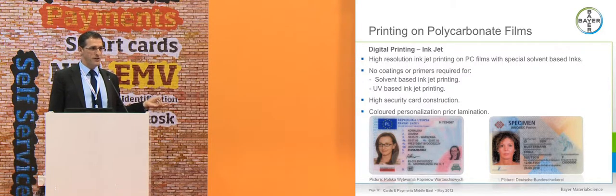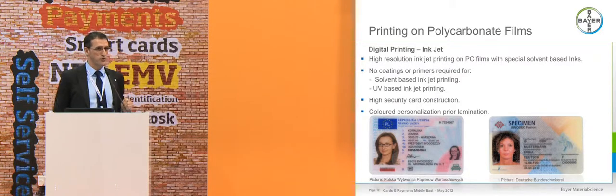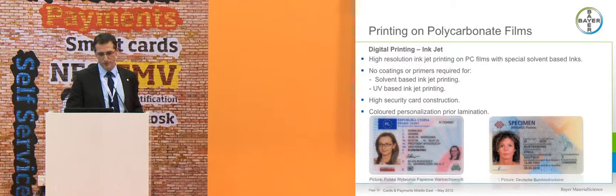The point here is the personalization of the document has to be done prior to the lamination process. So you first print on the document, then the offset printing, then you make the picture, then you laminate, and then the laser engraving will follow.